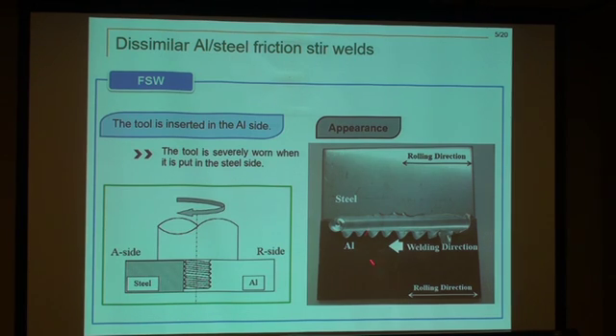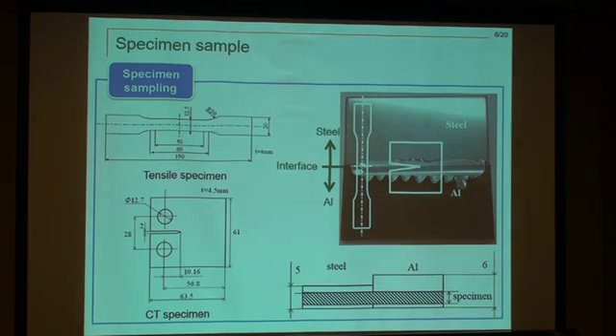And this is the appearance of the welded joint. As you see, the weld zone is formed in the aluminum side. And this is how we sample specimens. This is a configuration of the tensile specimen. This is the configuration of the CT specimen, which was used for the fatigue crack propagation test. And as you see, the specimen is sampled with the center line aligned with the interface of the joint. And to avoid the possibility that the specimen includes welding defects, we sample the specimen from the center in the thickness direction.